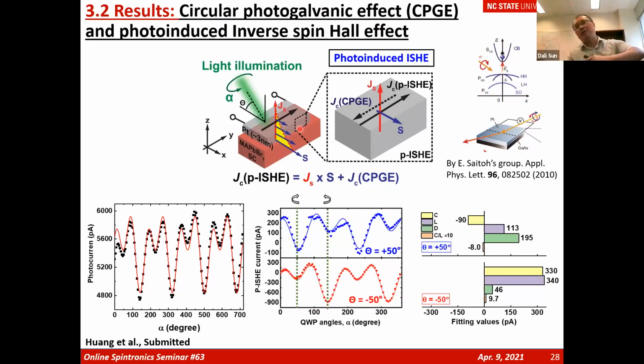If we reverse the angle, we see the C term, the second, the two sine 2 theta component, the circularly photogalvanic term really reverse sign from negative 90 to positive 300. This directly demonstrates that spin-dependent photocurrent has been formed under circular polarizations. Again, lots of inorganic semiconductor groups will not be satisfied with this statement, because if you want to prove a spin current in any material, show me Hanle responses.